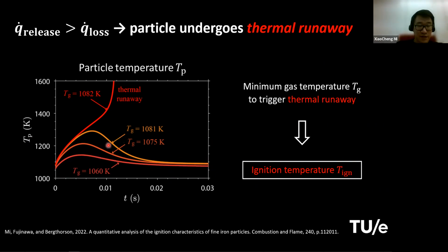gas. But if this gas temperature is greater than some critical value, you see this significant increase in temperature of the particle, and this is known as the thermal runaway, which means the heat release rate of the particle becomes greater than the heat loss rate into the surrounding. And if this happens, we know the particle is ignited, and the minimum gas temperature Tg that can trigger this thermal runaway is determined as the ignition temperature.